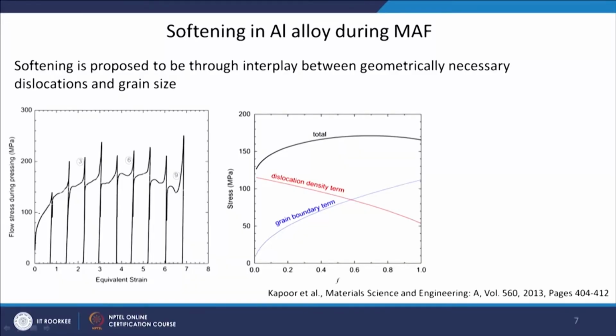Now, in some studies people have found that there is a softening during the deformation process. So, actually they have measured the flow stress during the forging process itself. These are not stress strain curves after the deformation, but during the deformation process. This is an aluminum alloy deformed at room temperature.